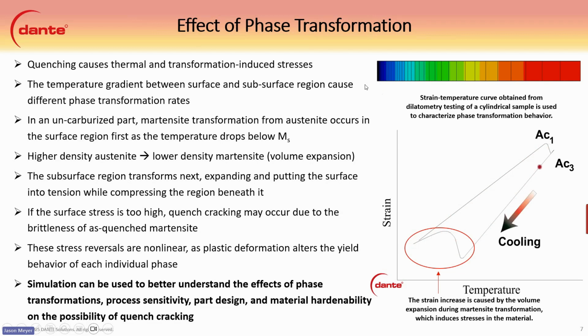And in an uncarburized part, the martensite transformation from austenite occurs where the temperature is the lowest. So here it would occur first at the surface when it drops below martensite start temperature. The higher density austenite transforms to lower density martensite, and there's a volume expansion. So you can imagine this area would grow when that martensite is formed from austenite. Then, once the subsurface cools down to MS, this one begins to transform, and when that transforms, it grows as well. This pulls the surface that has already transformed into tension. If the surface stress is too high, a quench crack can occur due to the brittleness of as-quenched martensite.